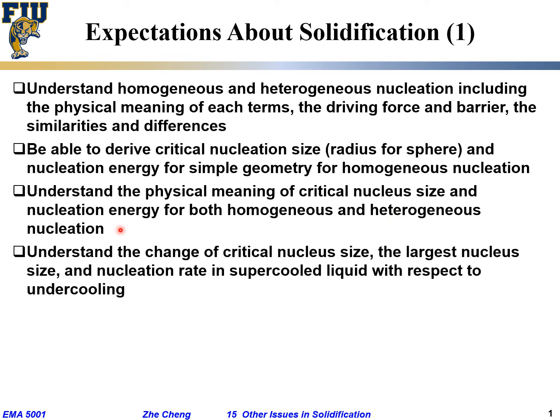I also expect students to understand the change of critical nuclear size, the largest nucleus cluster size, and the nucleation rate in supercooled liquid with respect to undercooling, which I just quickly mentioned. The larger the undercooling, the smaller the critical nuclear size, or that critical value when the first derivative of the Gibbs free energy change with respect to radius is zero. The slope is zero.